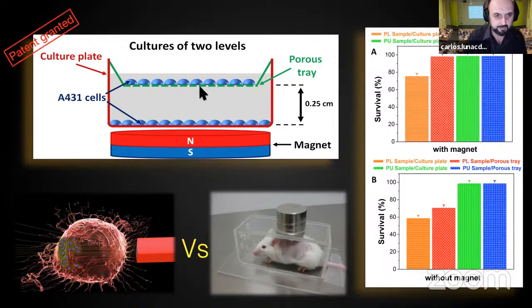These cells are separated by a porous membrane. So we can transfer nutrients and drugs between the 2 levels of cells. So we can do some experiments in order to analyze the effectivity of the transport of the drugs by superparamagnetic vectors. And we found that it's very important, obviously, the application of the magnetic field. Usually, the experiments use magnets with a constant magnetic field, but we observe that this process is optimized using pulsed magnetic fields, not continuous magnetic field.